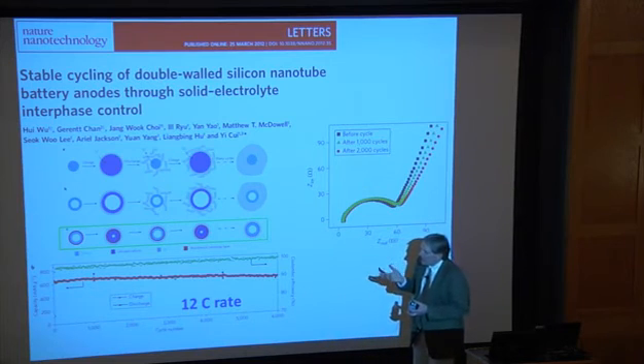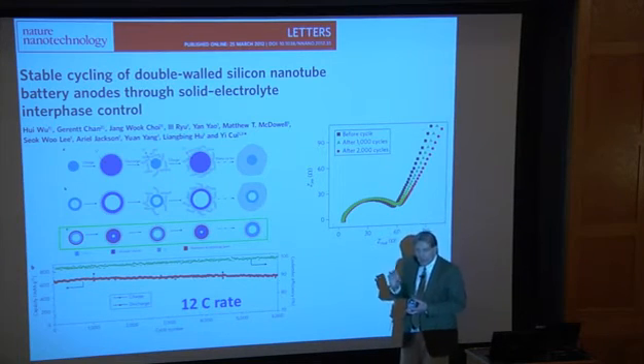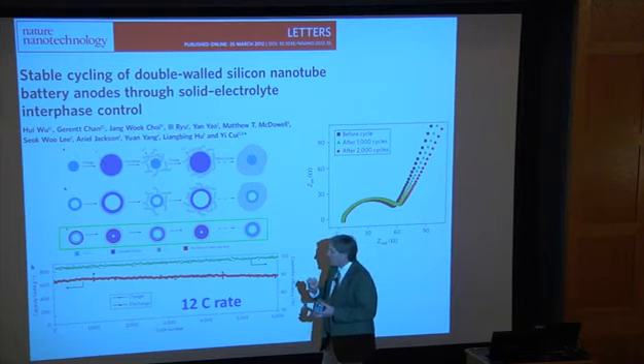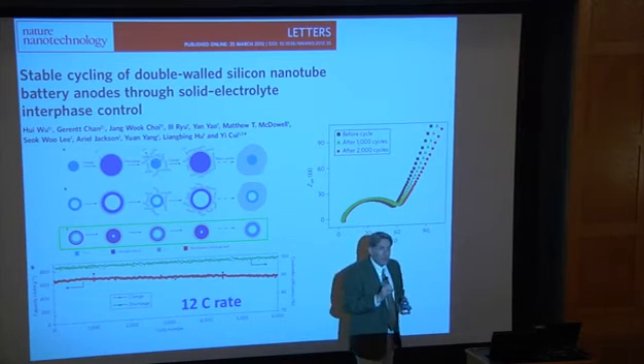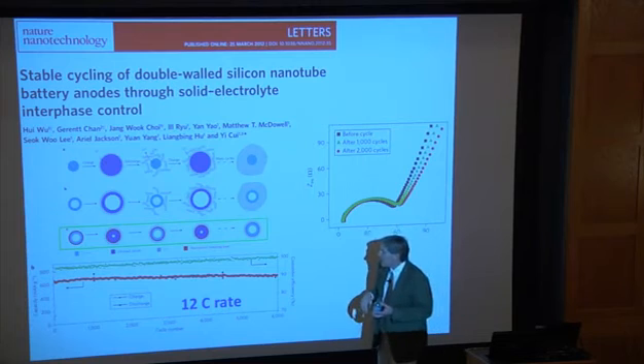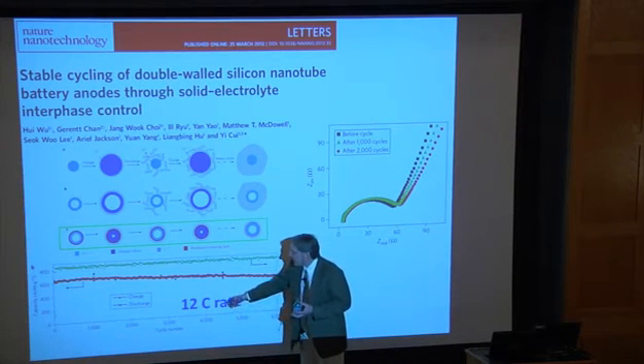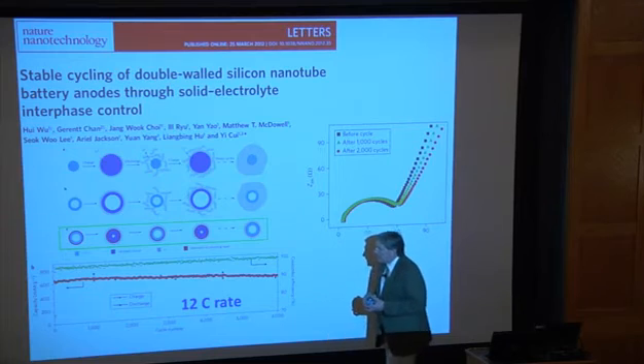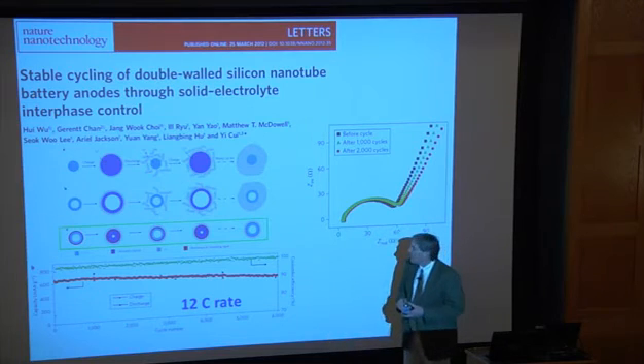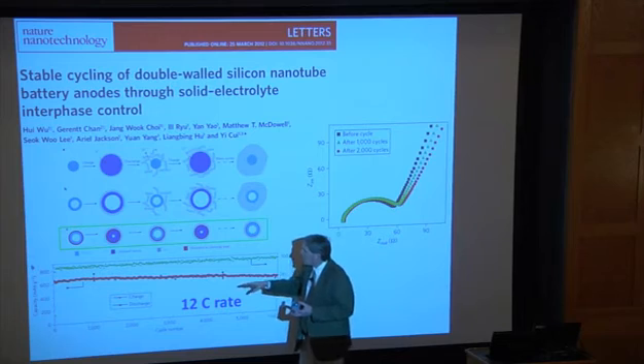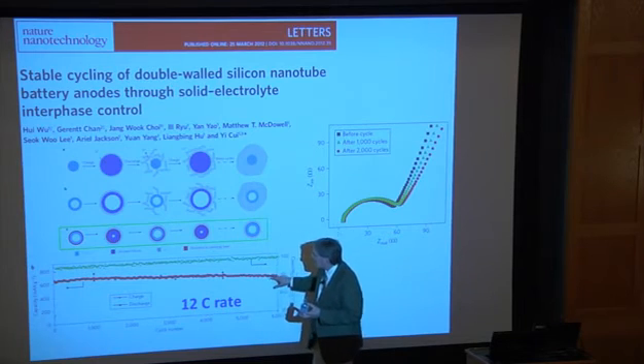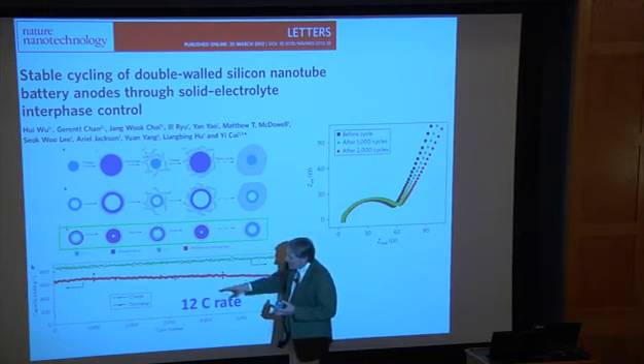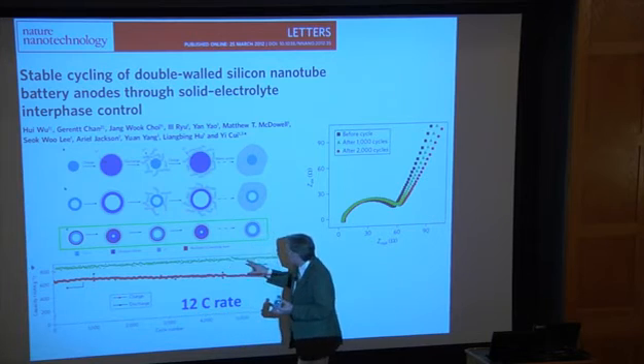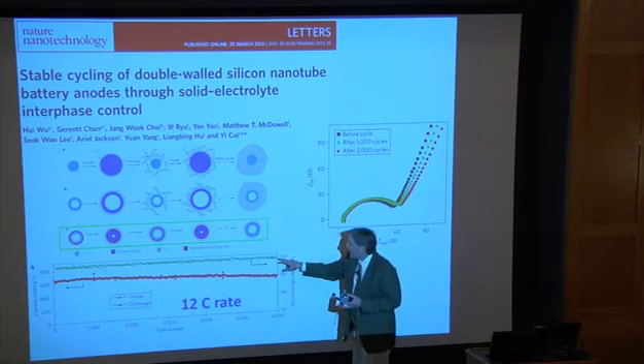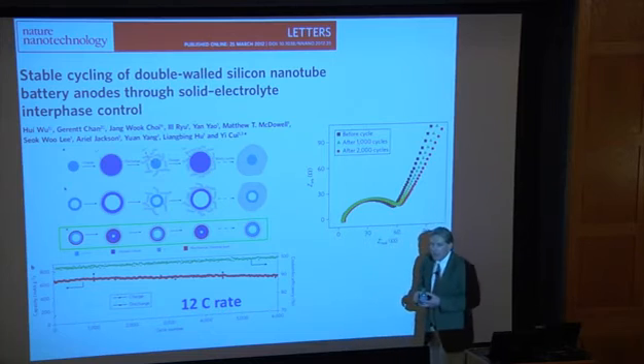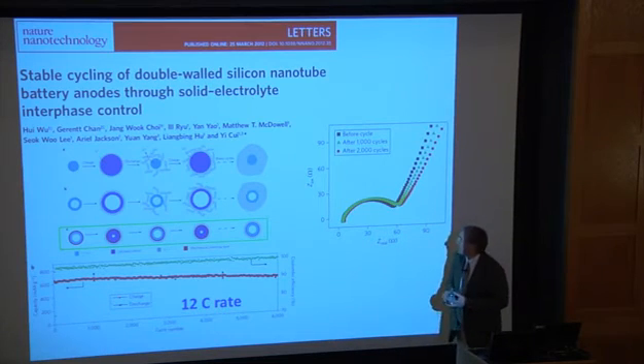Now the other thing is, because they're using extremely small geometries, the characteristic resistance to lithium diffusion is very small, and they could get very high rates in these systems. And so a 12C rate means they discharge the battery in a very short amount of time, 10 minutes or so for full discharge and charge. And they're maintaining their capacity at this very high rate at a fairly significant value, about 600 milliamp hours per gram. And their current efficiencies are generally quite good, although you can't resolve whether it's 99% or something higher. This is where a log scale would help out.